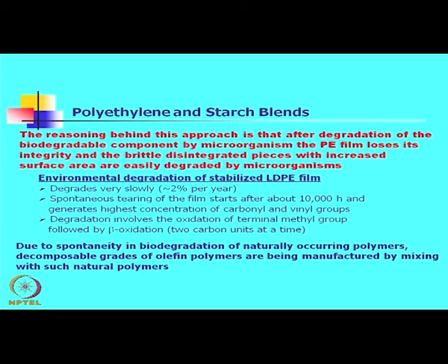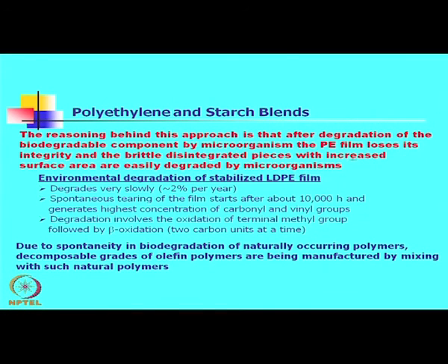So starch, which remains dispersed within the polymer film, will be eaten up and the film will become porous. It can be easily fragmented into smaller pieces, the surface will be increased, and the microorganisms will degrade the film at a much faster rate.